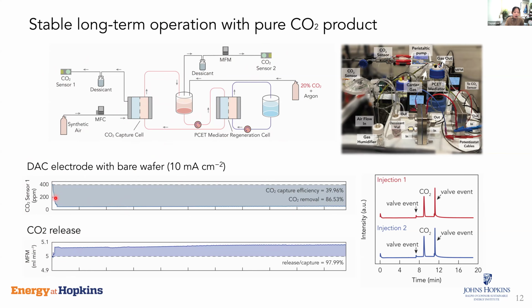So as you can see, this is versus time. The course is 50 hours. We demonstrated really consistent performance for our capture side. We have a CO2 capture efficiency of about 40% and above 85% of CO2 removal, and the performance is really stable. And as you can see from the CO2 regeneration side, we're constantly generating a very stable output of CO2, with the amount released versus amount captured being about 98%, indicating that this process is highly reversible.